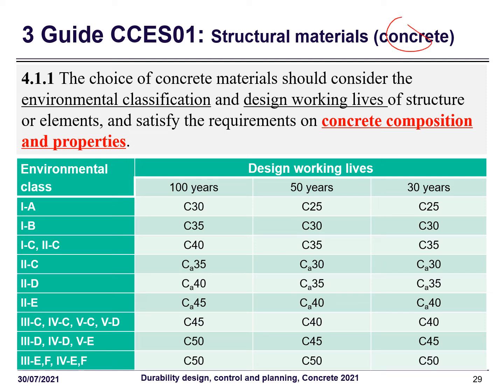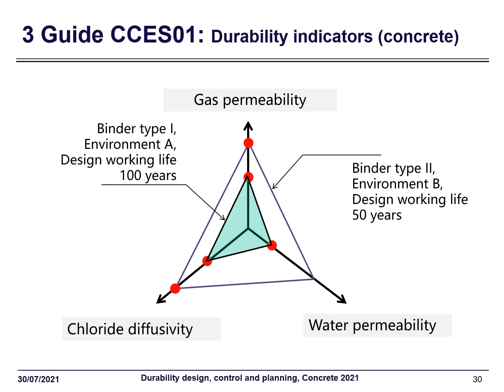For concrete, the requirements are formulated on the basis of environmental classification and design working lives, and the requirements are formulated for both concrete composition and properties. The most important property here is the minimum strength for concrete. And in parallel, we introduced the concept of durability indicators like chloride diffusivity, water permeability, and gas permeability. Because we think that whatever the durability phenomenon is, it more or less relates to gas transport, ion transport, and water transport.